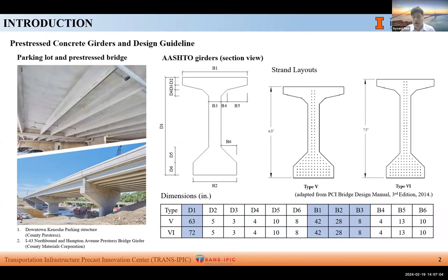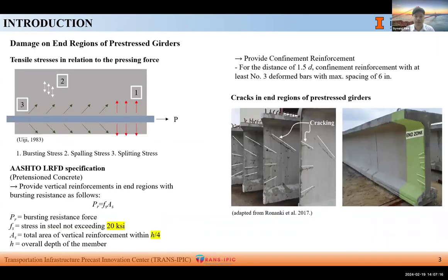So by constructing girders with large width and narrow span using numerous strands, concerns about pre-stress release are emerging in pre-tension concrete fields. Uiji in 1983 suggested a stress model for pre-stress release. Bursting stress, spalling stress, and splitting stress are those that develop near the end region, which induce cracks.